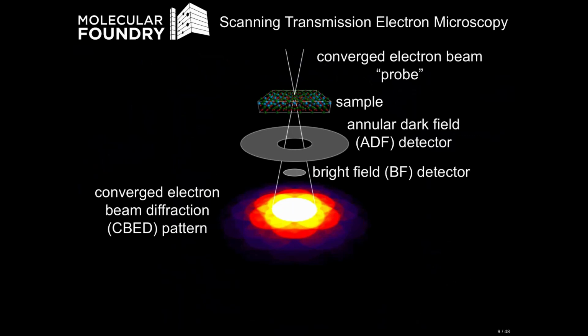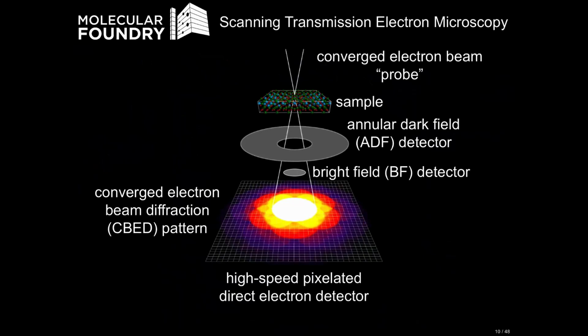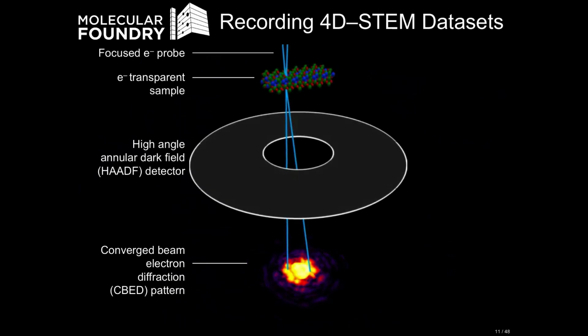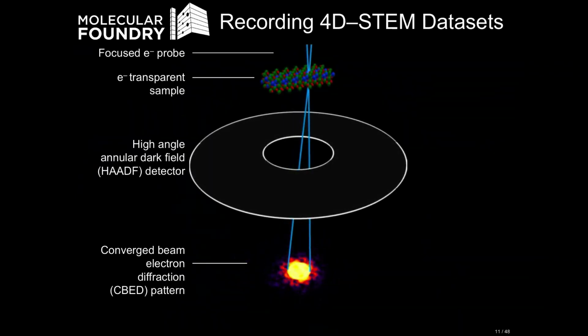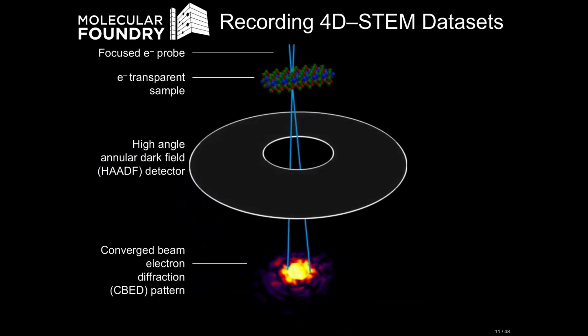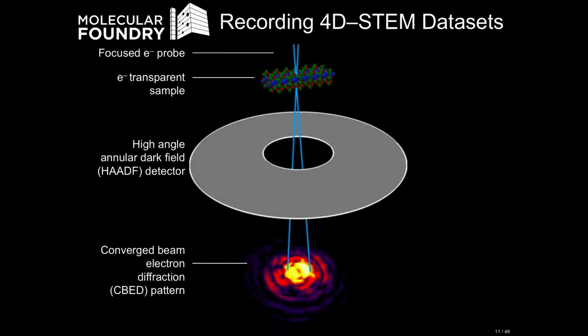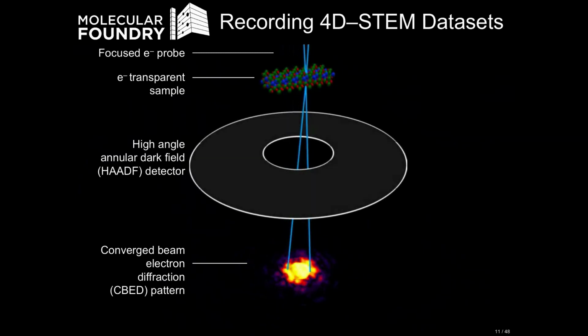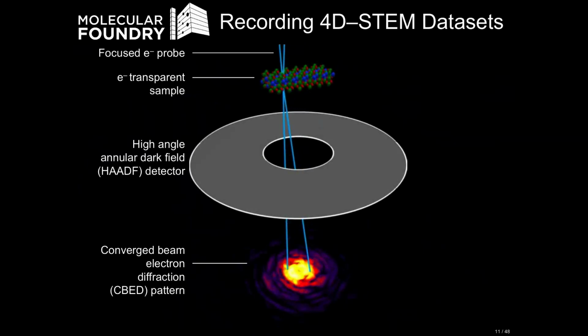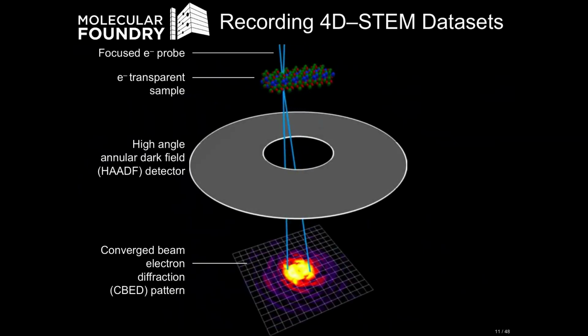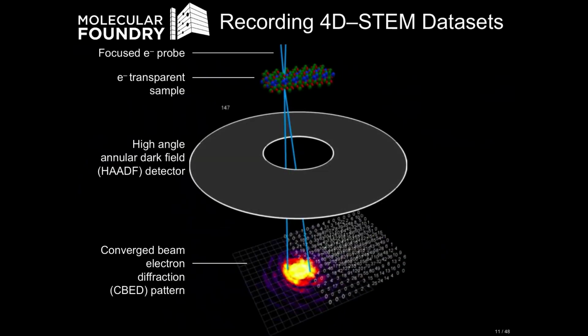So the recent introduction of these direct electron detectors, they run at high enough speeds that if we place one in the far field, we can record every single pixel of the diffraction pattern under each STEM probe. And so if I just play this movie here showing what it looks like, as you scan your beam across the sample using the STEM scan coils to move it around here, you get a scattered signal on your high-angle annular dark field detector, but you can also use the high-speed direct electron detector to record the full pattern here.